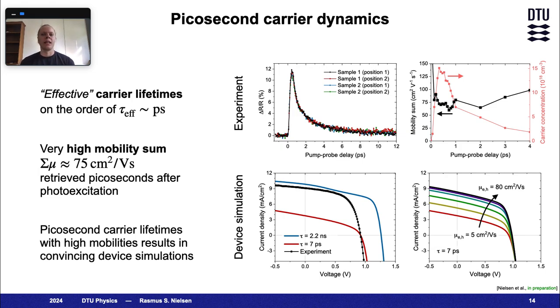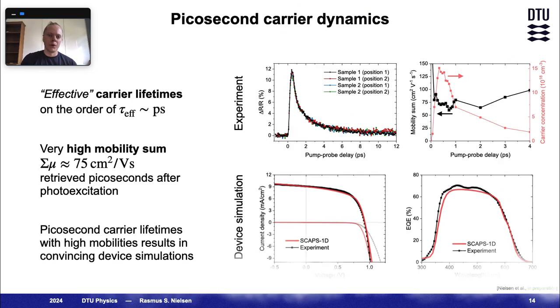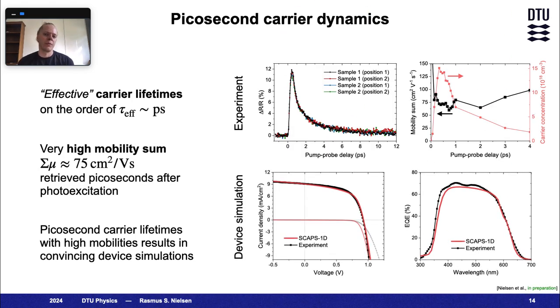By changing the carrier lifetime from nano to picoseconds, we see that the experimental open circuit voltage quantitatively matches simulated values, and by increasing the carrier mobility accordingly, the fill factor and short circuit current started looking more right as well. If you for a second buy the premise that the initial decay in our terahertz transient corresponds to that of the free carriers, and the longer decay corresponds to some form of carrier localization, potentially through defect trapping, then the device simulation actually agrees, both in terms of current voltage and quantum efficiency measurements.